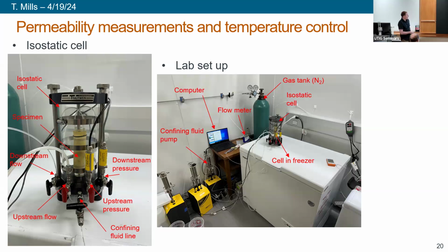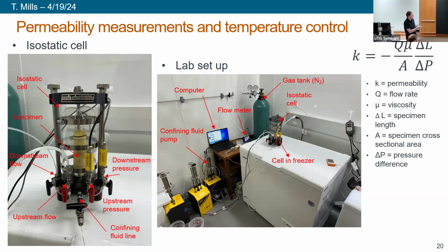And then this is our lab setup where we have our cell, we have gas, flows in through the cell, up through the sample, out, and then the flow rate gets measured here, and we have a computer to gather all of our data. And the most important part, since we have frozen samples, our cell here is going down in this chest freezer where we're keeping the sample at around -2 to -4 degrees Celsius. And then, of course, we use Darcy's equation to solve for permeability.